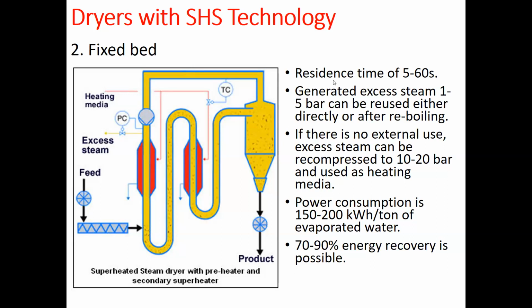The residence time is about 5 to 60 seconds. Very, very fast. And the generated excess steam, 1 to 5 bar, can be reused either directly or after reboiling. And if there is no external use, the excess steam can be recompressed to 10 to 20 bar and used as the heating media. And the power consumption is about 150 to 200 kilowatt hour per ton of evaporated water. And about 70 to 90% of energy recovery is possible.